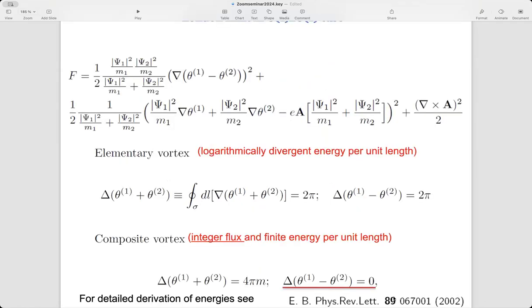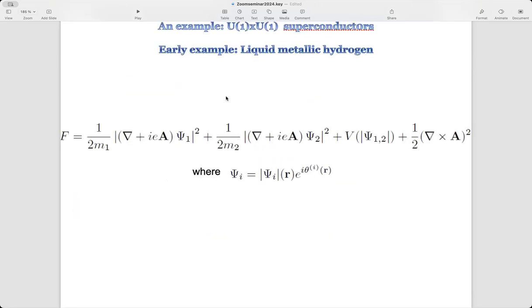And one can find details in this old paper, now almost a quarter of a century ago. The important thing is that one can fractionalize the flux quantum of such a system. And the reason flux quantization is no longer universal in the system is basically frustration. If one looks back at this basic London model, what is the origin of the usual flux quantization argument? If one would have only the field psi, one winds the phase of this field by 2 pi, one gets a gradient of this phase, and then one can asymptotically compensate this gradient away from the vortex core by enclosing one flux quantum and getting a finite energy solution.